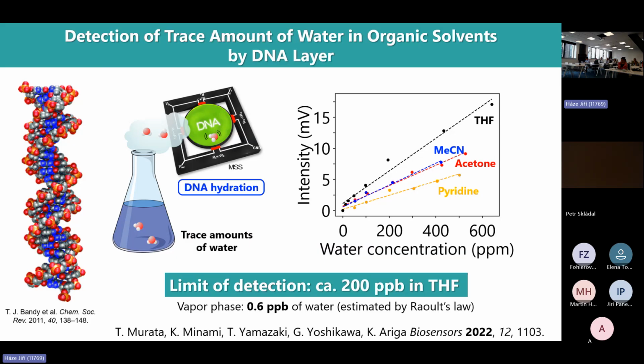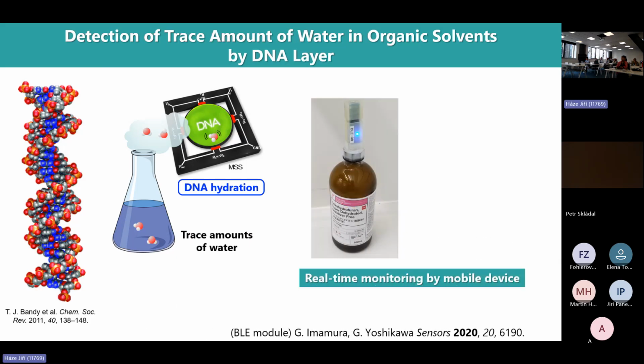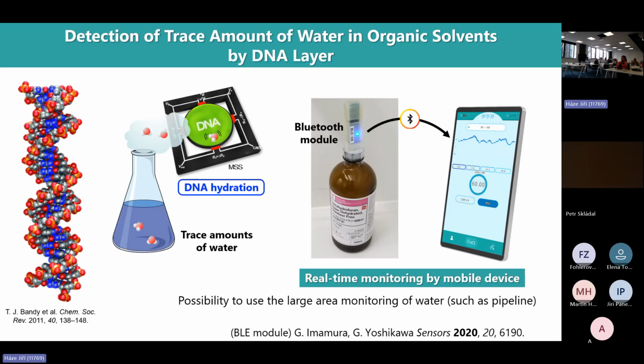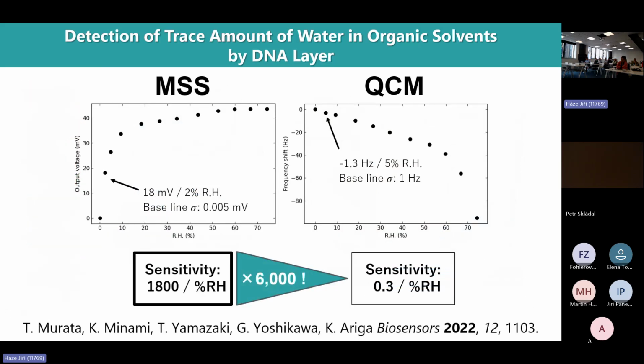Water contamination in organic solvents makes a huge mess in organic synthesis, and usually we use Karl Fischer titration to measure it. But in this case, we can simply measure the vapors of the solvent and detect the water, even in a trace amount. So we developed a Bluetooth module that can be attached directly to this bottle, and we can detect the trace amount of water. And we compared with the QCM under the same conditions.